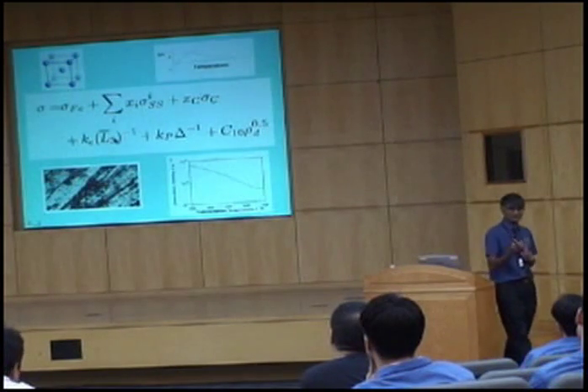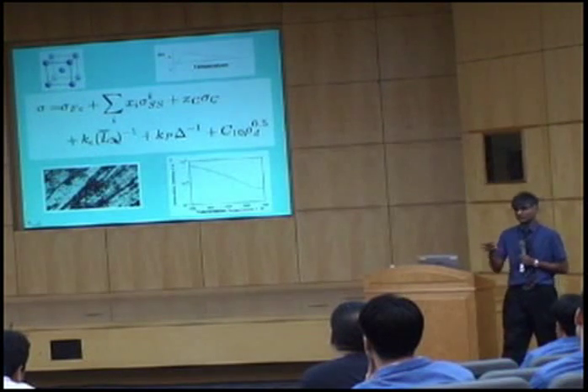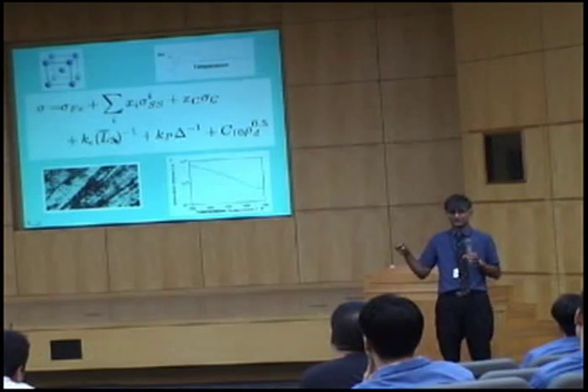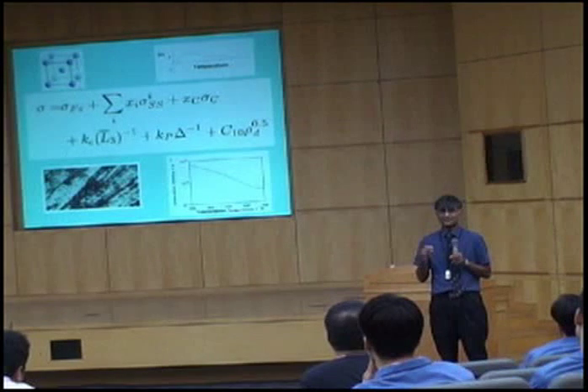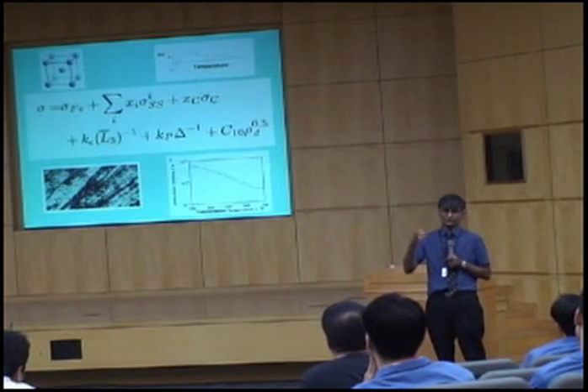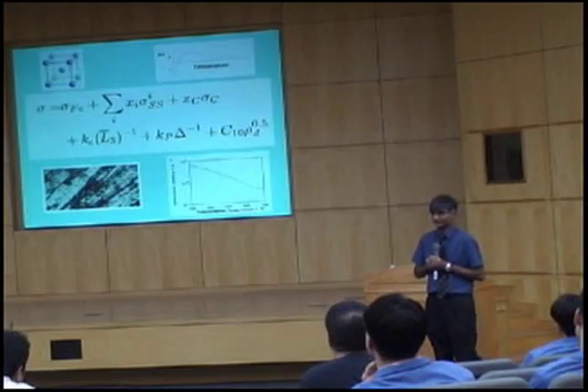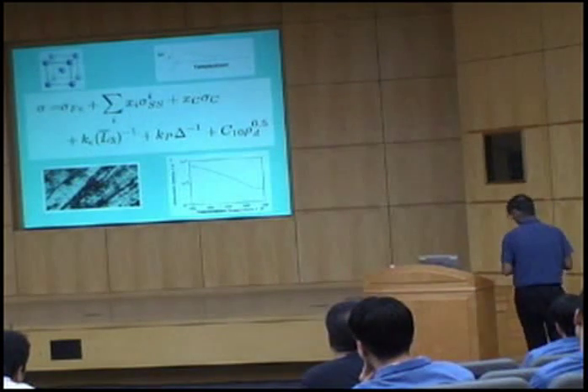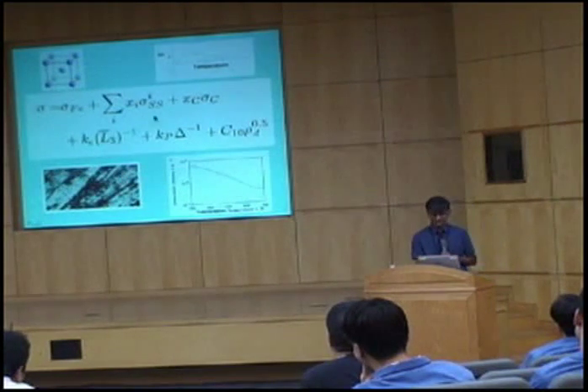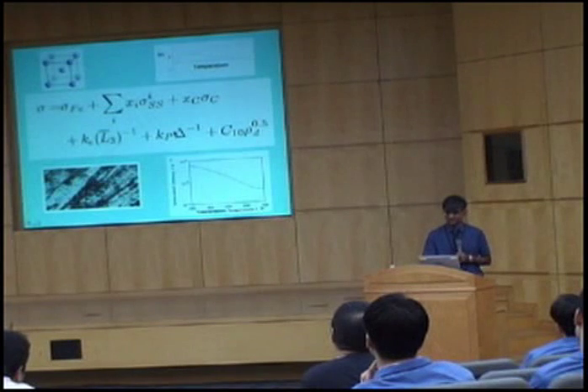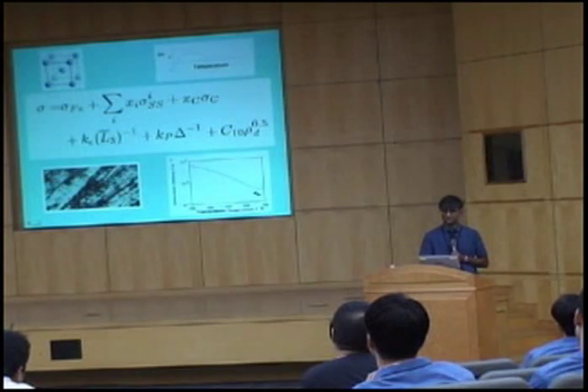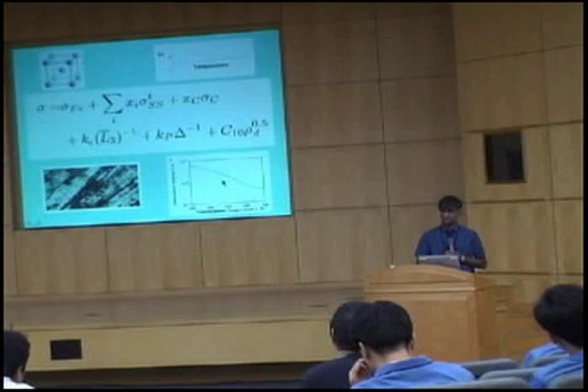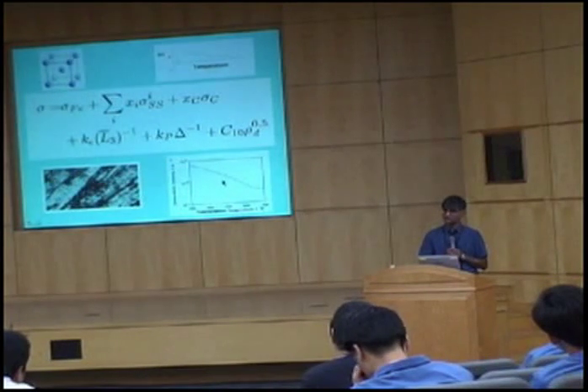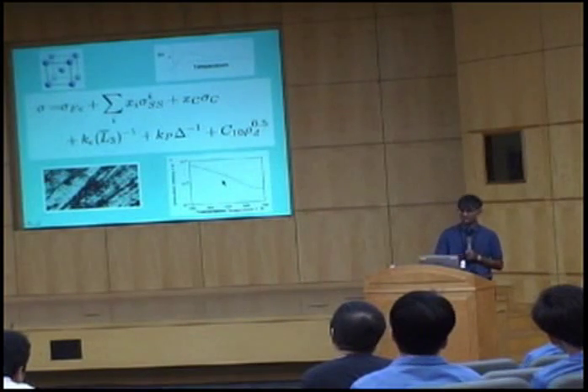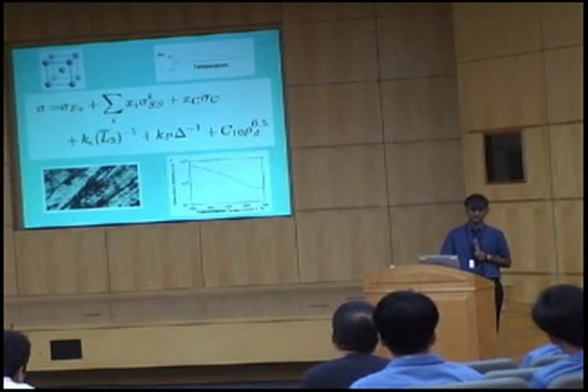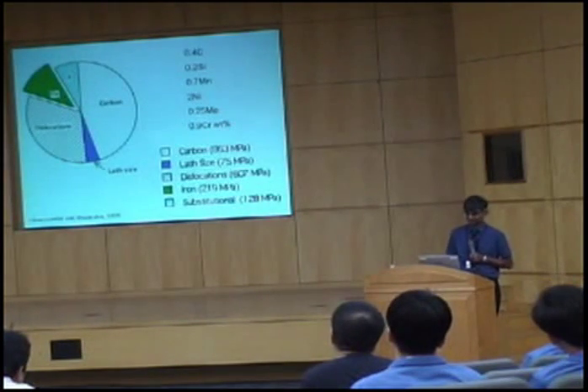The grain size of bainite is not like the normal grain size. We have plates, so it doesn't quite obey the Hall-Petch equation. The strength varies with 1 upon the thickness of the plates, and we will see why. You can have precipitation hardening, for example, in the creep-resistant steels, and of course, there's a dislocation density which is created by the plastic accommodation of the shape change, which also contributes to the strength. So let's have a look at all those components one by one.